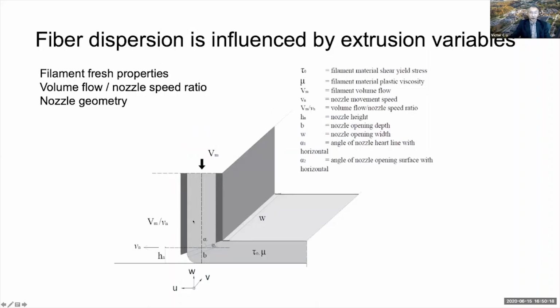During the extrusion process, the quality of the printed filament is directly related to the fresh properties of the ECC, including, for example, the yield strength and the plastic viscosity of the material, as well as the ratio of the volume flow of the ECC material to the nozzle speed. And finally, the nozzle geometry also plays a role in controlling the quality of the printed filament.